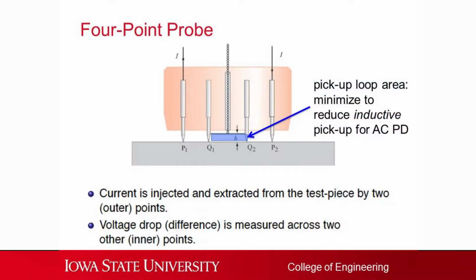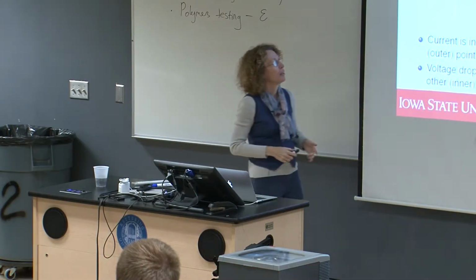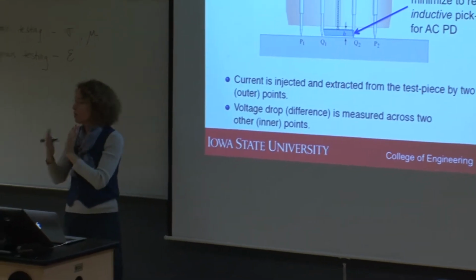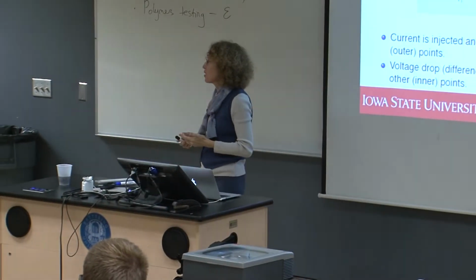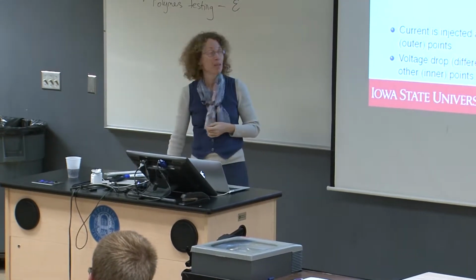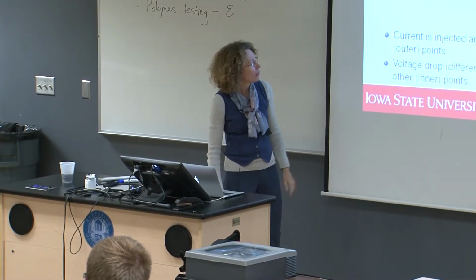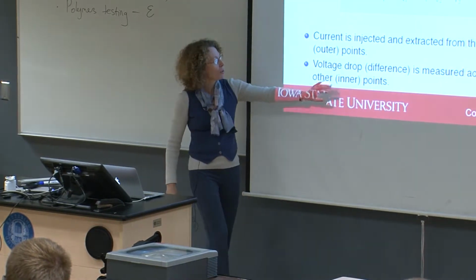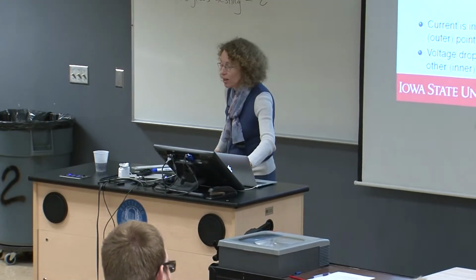Okay, good. All right, normally we do this in a kind of quasi-DC type way, but if you use a broadband approach, so you change your frequency, you can actually get more information out of the material. And if we do that, we then have a little pickup loop here we have to worry about. So we just try and make that as small as possible because this will give us some contribution to our measurement, but it doesn't tell us anything about the material. Okay, so that's something we want to minimize. So I just mentioned that there. Okay, so we're going to measure potential drop across these 2 points and find something out about the material.